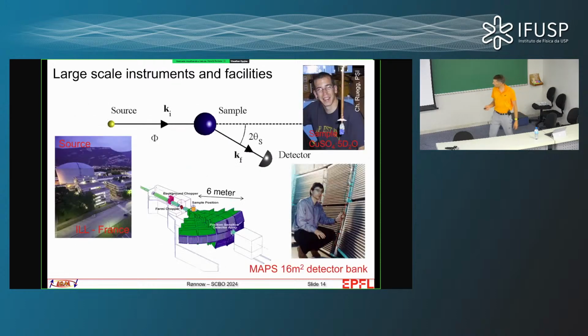It's a little bit more inconvenient in reality because the source of neutrons is not a little yellow dot on a screen. You actually need a large facility such as a nuclear reactor. This one is in Grenoble. In order to have enough counts, you need a large sample. This is a PhD student who went on to become the director of the main national lab in Switzerland. And that, by the way, is the same or a similar blue crystal to the one in the previous photo, and he's very happy about that. Then you need a detector, which is not a little thing. Here's one instrument where you have a 16 square meter detector.